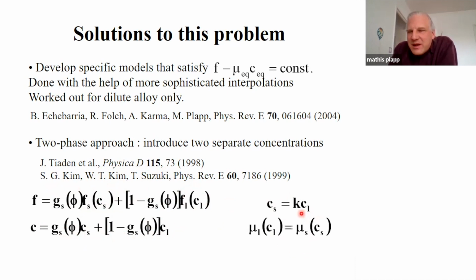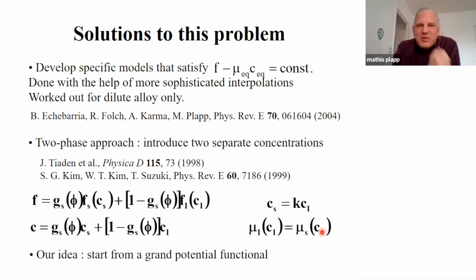And you can do this by either relating directly the solid and liquid compositions. This is the dilute alloy approximation. Or in the general case, you have to require that the two chemical potentials in liquid and solid are the same. Okay? This works perfectly fine. The disadvantage is that you have a system of equations to solve at each space point, so it's quite heavy. And so the new idea that we put forward 10 years ago is that actually all this is far easier to formulate in the grand potential function.